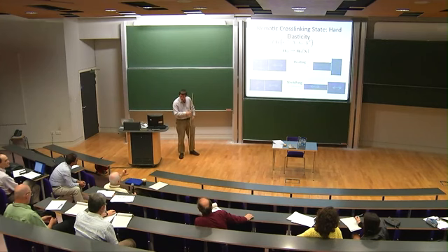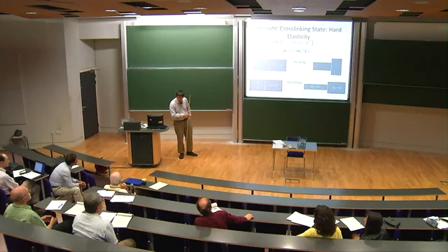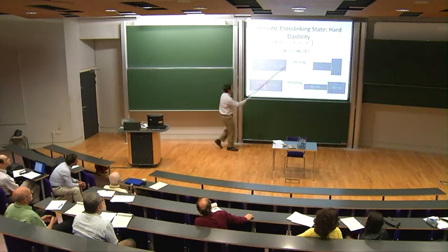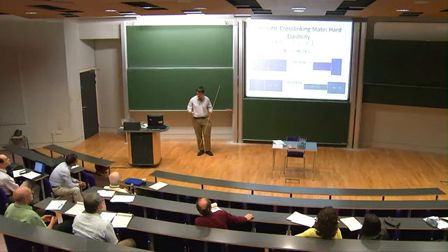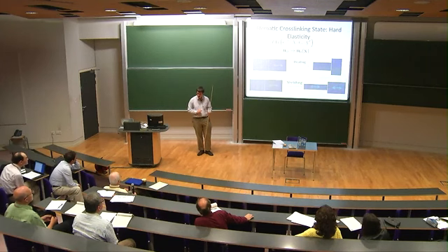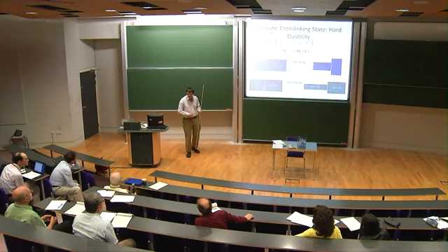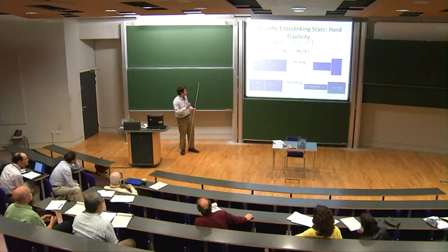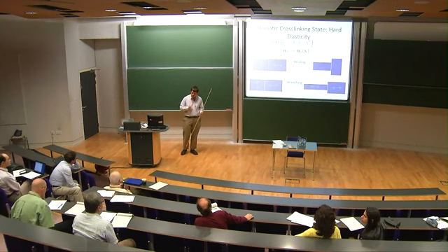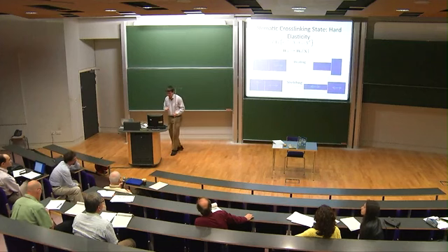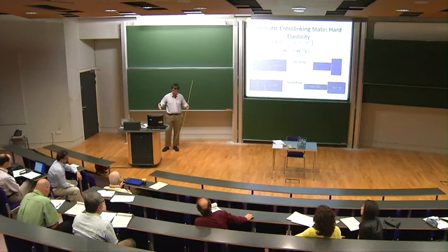Sorry, I guess I'm really confused about something stupid. If I'm in the nematic phase and it's equilibrium, N naught doesn't depend on X, does it? Oh, so N naught depends, so if I have a nematic liquid, for sure, if I wait long enough, I think it does turn into a real monodomain. But at any finite time, it has a wonderful disclination pattern in it. And then when I cross-link in, that's what appears. So I see, you're doing it in an inhomogeneous nematic. Oh, yes. So if you start with a perfectly oriented nematic phase, then you're absolutely right. But then you haven't got a polydomain at all, I think. Then you have something that starts with long-range order.